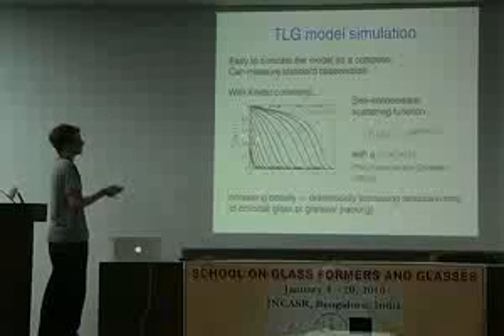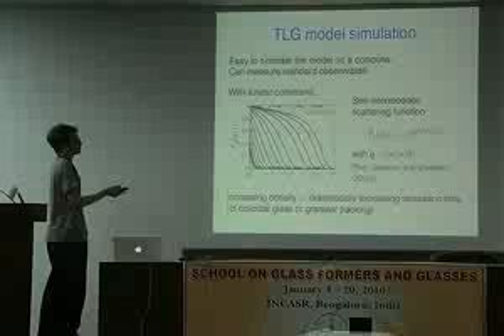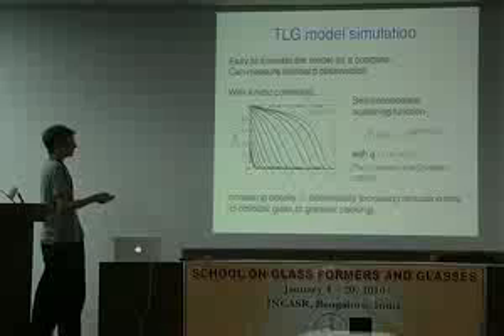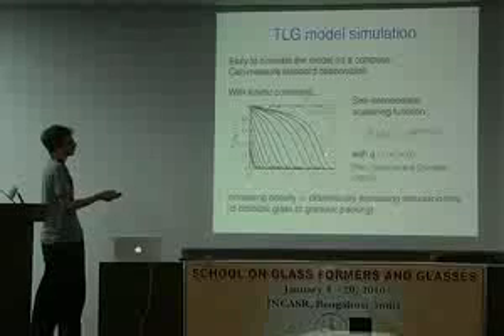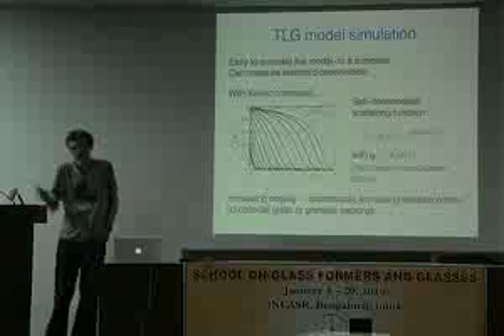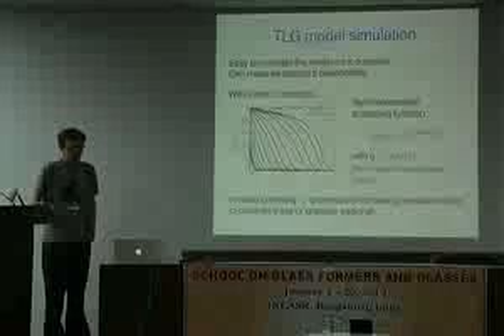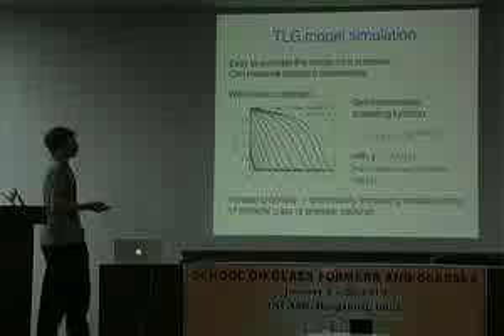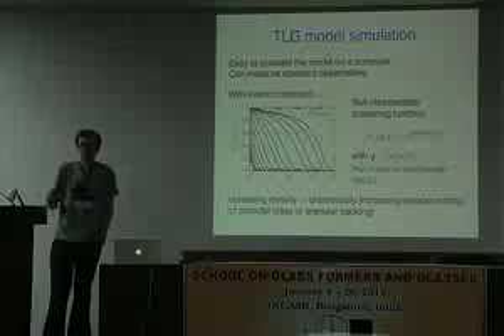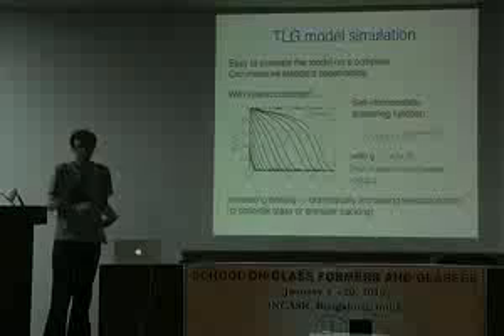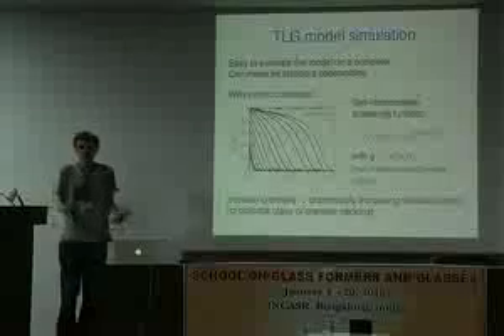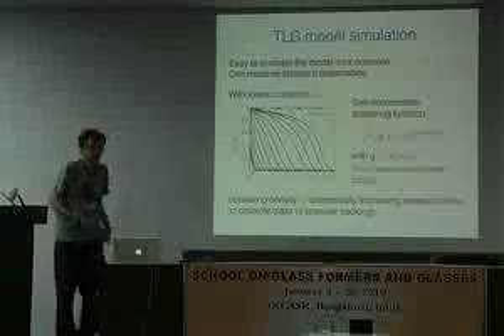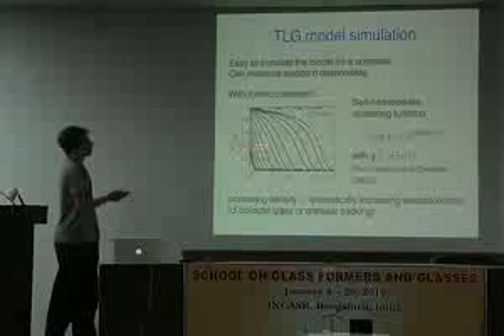And as I increase the density towards 1, so I guess this is about 20% density, and this is probably about 80% density. As you increase the density, the relaxation time increases from a number which is basically 1 to a number which is somewhere around 10 to the 7. So you've got a large change in relaxation time with a changing structural parameter. And that might remind you of some kind of colloidal system or some kind of granular packing. So basically the only physics that we've put in is crowding, and we've managed to arrive at some rapidly increasing length scale.